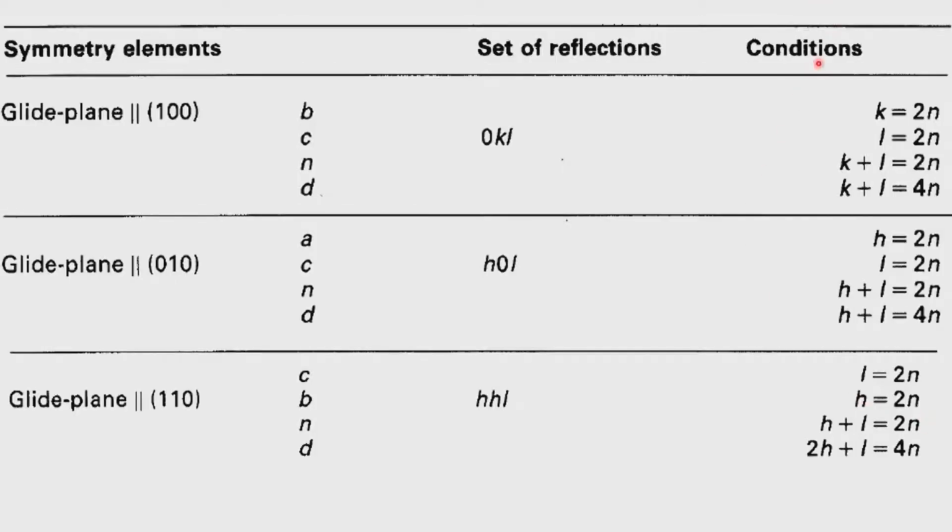But what is present is more important from the point of view of the diffraction condition, and therefore the presences are listed here. International Tables for Crystallography will list only the systematic presences, what are present systematically. All right. So, this is as far as the glide plane is concerned. We have seen the lattice centering, and now we have seen the glide planes. Glide planes give systematic absences associated with projection reflections. The general reflections' systematic absences give the lattice centering information.